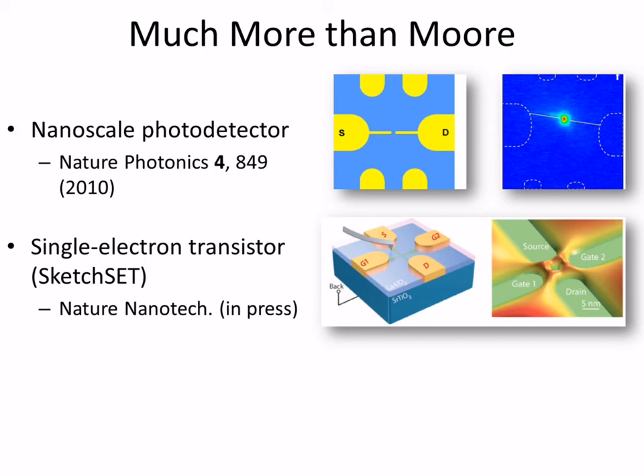It's interesting that this system actually works at relatively high temperatures, tens of Kelvin. It's also interesting that the strontium titanate in that temperature range is ferroelectric, so it looks like the barrier regions are behaving in a hysteretic fashion, allowing you to switch between the Coulomb blockade region and the resonant tunneling regime simply by altering the ferroelectric polarization in the barrier. So this is a very interesting system because it's at the smallest scales, literally single electronics.